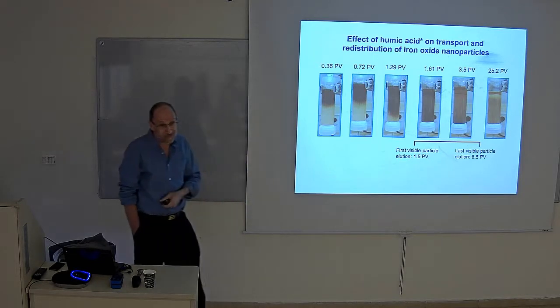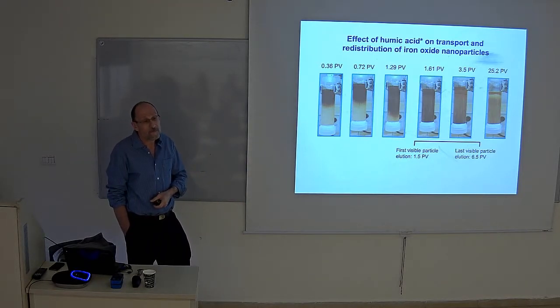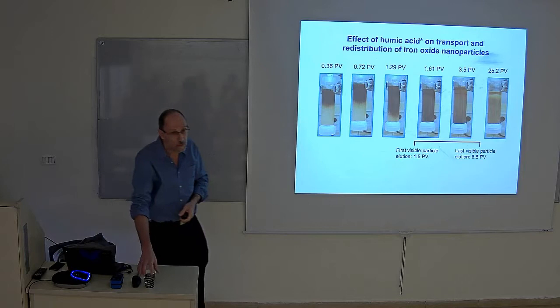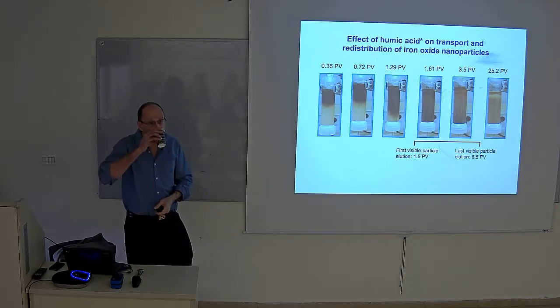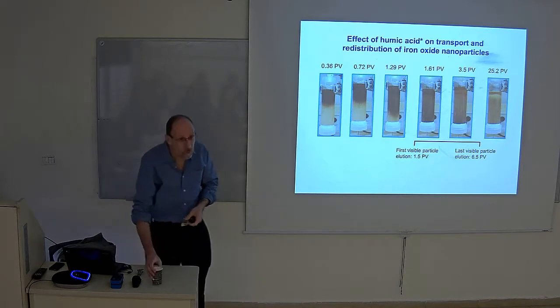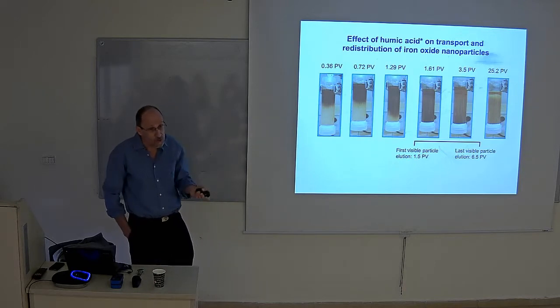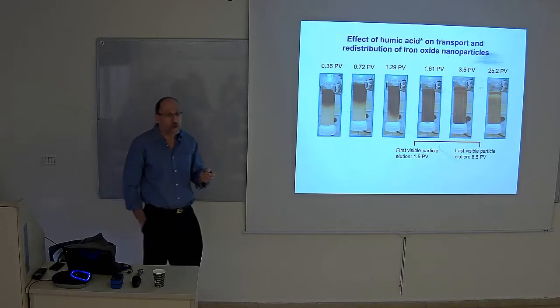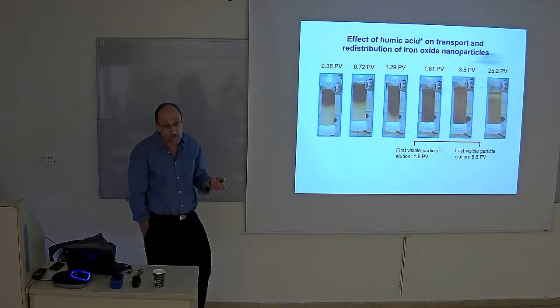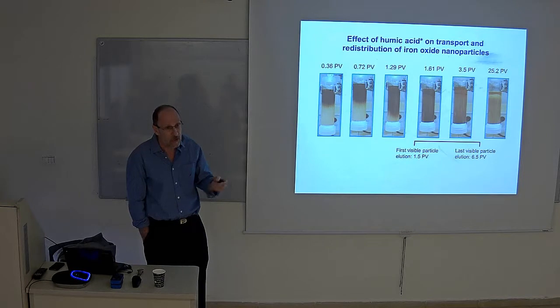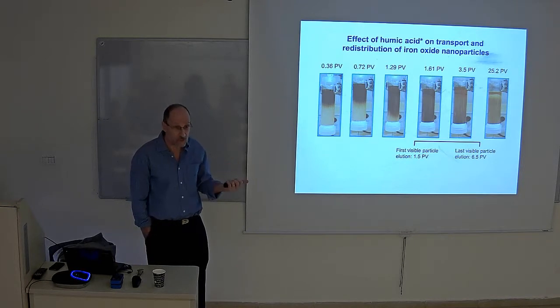So, in the literature, people are talking about the movement of particles. Well, they didn't term them nanoparticles at that time because the term was not available. Yeah. Microparticles or small particles. Everything is dependent on the surface charge. Right, but if you look at the literature on colloids, on larger particles, they behave differently. All the analysis that's being done, people are using colloid filtration theory, for example, to try to analyze how nanoparticles move, and it doesn't work. In fact, DLVO theory now has been shown it's not relevant, generally speaking, to nanoparticles.